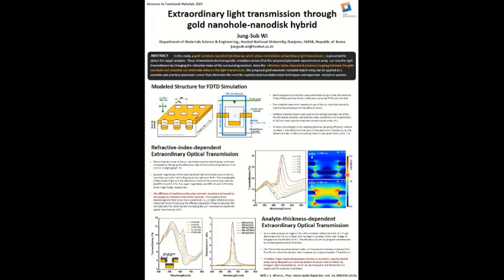This colored image shows the calculated E-field contours around these nanostructures. And this colored image shows that the local E-field is significantly enhanced by increasing the refractive index from 1.0 to 1.5.